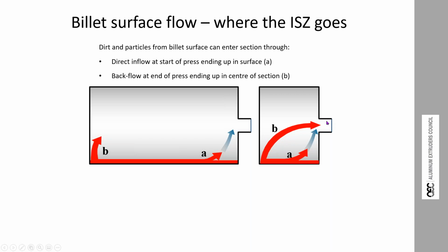Now, if you're making automotive sections, or something which is going to be machined, this is a major weakness. If you're making window frames, it's not such a big deal unless it's very pronounced. The inflow at the front, the type A inflow, is a real big deal if you're making window frames which are going to be anodized. So it depends a little on your market, which is the more serious. The big trick to controlling the type A inflow is to make sure your container liner temperature remains stable. And this means you have to be able to suck enough heat away, and I'll come back to that in just a minute.